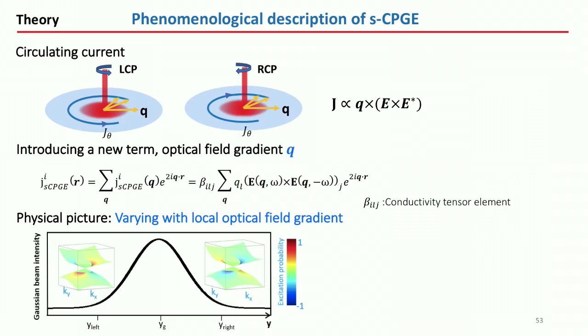So this means you have to derive new response functions taking into account the spatial inhomogeneity of the optical beam. In short, the reason why this happens is, in the regular conventional circular photogalvanic effect, the response function is given by the current proportional to E cross E star, where E is a complex field. So for right circularly polarized light, E cross E star goes in one direction; for left, because the sign changes, the current goes in the other direction. But in our case, because of the inhomogeneous profile of the light, this produces an in-plane momentum Q vector, which is in the radial direction of the optical field. So because of this Q cross E star, we can produce this circulating photocurrent. So this is the phenomenological description.